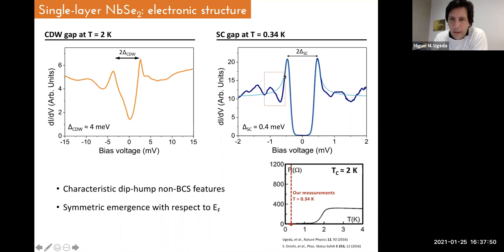But if you look more carefully outside of the gap, the conductance outside the gap does not fit the BCS model. And actually what we see instead are prominent dip-hump features, several of them, in general symmetric with respect to the Fermi level and in general equidistant with respect to the main coherence peak.